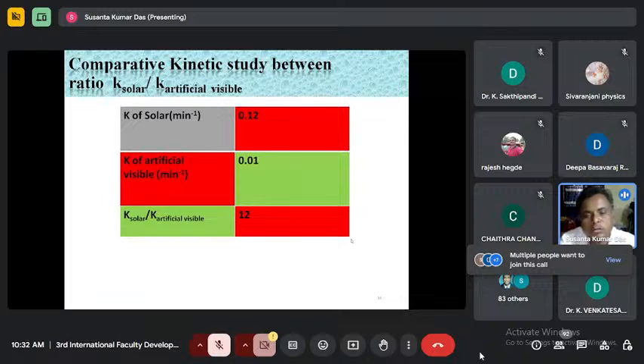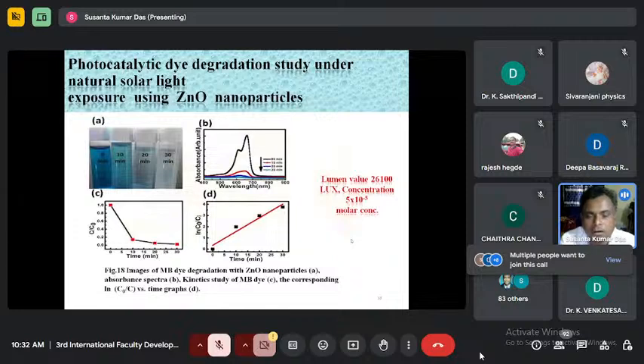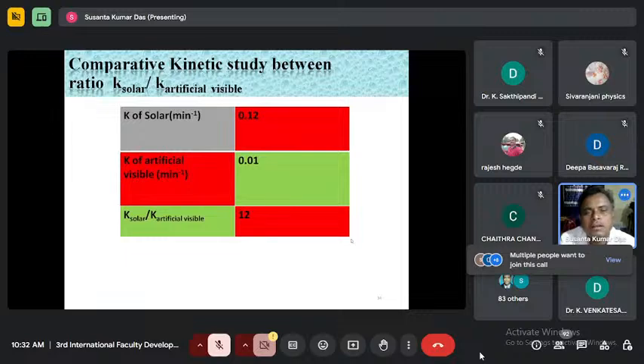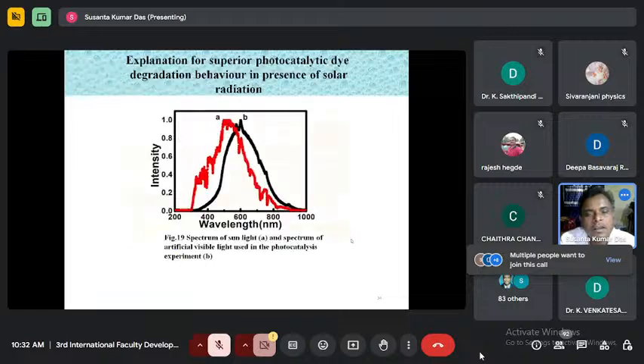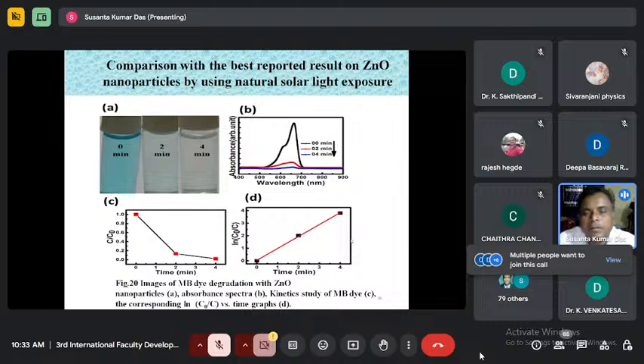The reason I'll tell you, and here also we found that when we did the experiment with visible light, and this is with the solar light, we tried for a comparison. We tried to find the reason why in normal artificial visible light we didn't get good results, but in the solar we got good. Then we tried to compare the spectrum. I had a spectrometer from another project of mine from a CRB. So I tried to see the spectrum, and I found that the B curve stands for the artificial visible light, whereas A stands for the sunlight. So the sunlight spectrum has a significant amount of UV radiation, you see. Therefore, we got very good photocatalysis in the solar radiation. So that was also published. All details about the publication I'll show you next.